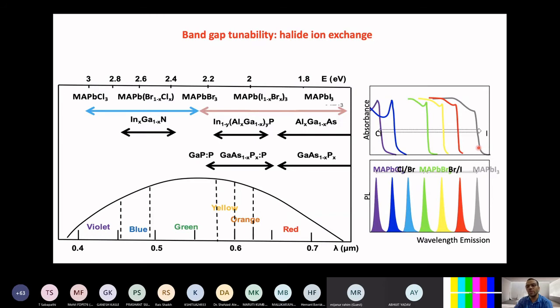This is the UV absorption data of the different perovskite semiconductors. There is one more interesting thing which we can observe here: as you go from iodine towards chlorine, you find your absorption spectrum band edge. If you can see this laser cursor, at this point there is no additional peak, but this peak starts becoming more dominating and significant as we go from iodine to bromine to chlorine. So when you go towards the smaller halide ion, you find your absorption features start dominating with one excitonic peak. This is the classical excitonic character which is seen in semiconductors.